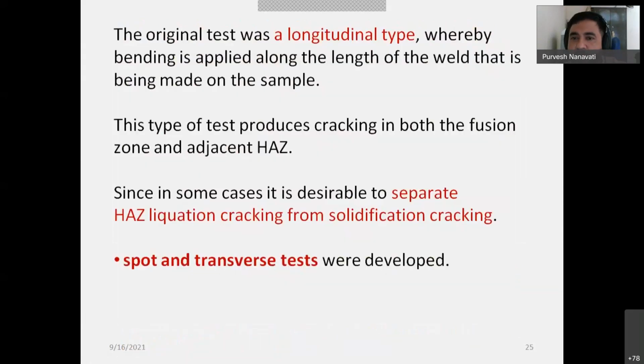Now, moving ahead, it is sometimes very essential to know whether the crack is originating from the fusion zone or from the heat affected zone, or whether it is a HAZ liquation cracking or a solidification cracking. Because we knew from the previous slide that solidification cracking takes place in the weld metal most of the time, and liquation cracking takes place in the heat affected zone. So it is difficult to separate them out, and this is a limitation of this test. So spot and transverse tests were developed. I told you that over a period of time, from the basic test setups, many modifications were made, and out of these, spot and transverse tests were developed.